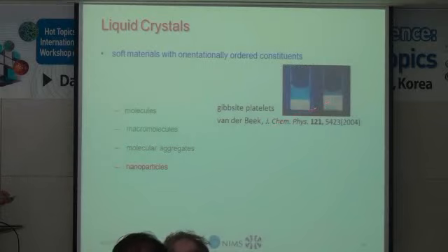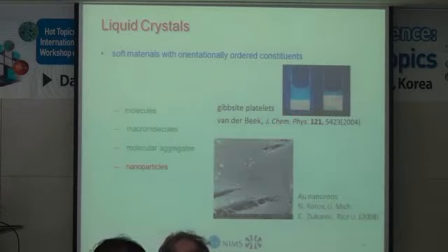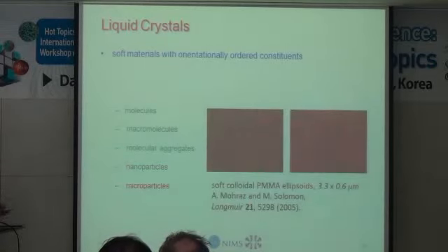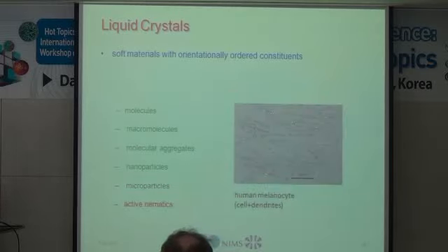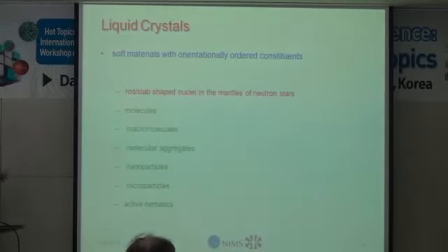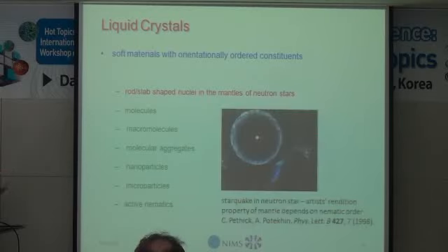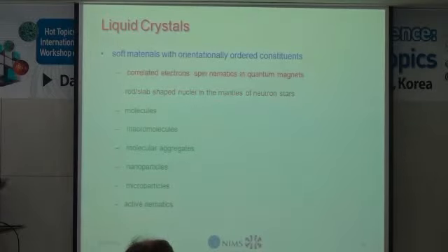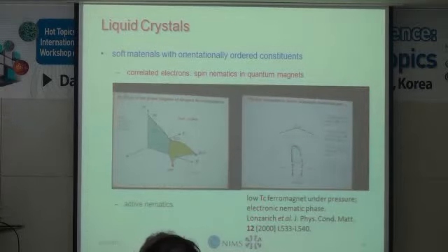Nanoparticles make liquid crystal phases, both naturally occurring minerals and man-made nanorods and things. Microparticles form liquid crystal phases, so these are micron-sized particles made by Mike Solomon at Michigan. There are active nematics, which consist of biological entities which swim around, but they form ordered liquid crystal phases. So, and of course one can go in the other direction in the length scale. It turns out that the nuclei in neutron stars, which are really very high density materials, these nuclei form liquid crystal phases, and the mechanical properties of the mantle of neutron stars are predicated on the liquid crystallinity of the material. And finally, on a very, very small length scale, even correlated electrons, that is, electron spins, form liquid crystal states. So, and this is work by Gilbert Lonzarich at Cambridge on this.